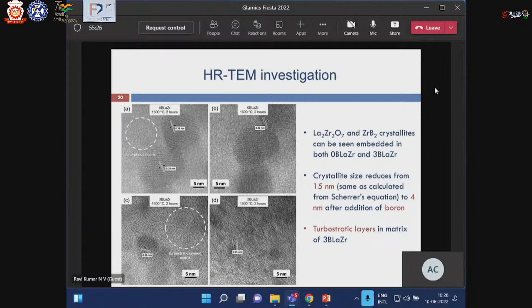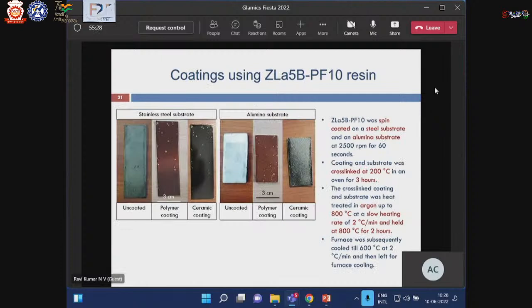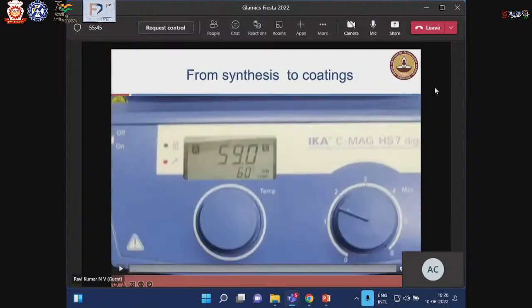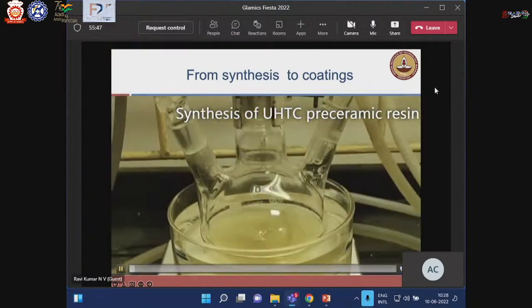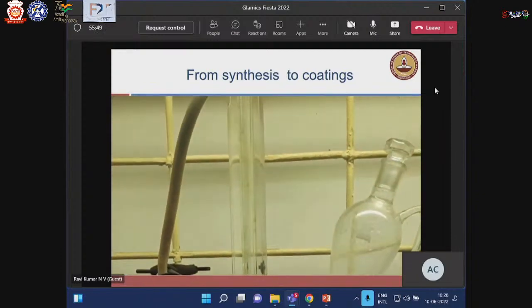We have already produced coating formulations and tried to coat these materials on stainless steel substrates, ceramic substrates, and so on. The idea is that we make these coatings without any bond coat. So we coat them with precursors and subsequently convert them into amorphous ceramics. I'm just going to show you a video, maybe, that will help you understand better how we do this.